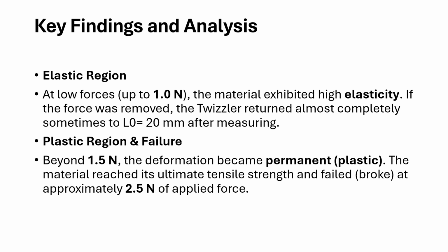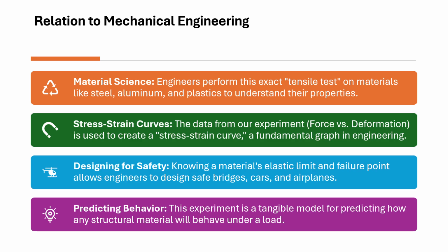So for the plastic region and failure of the Twizzler, it was beyond 1.5 newtons, where the deformation became permanent or plastic, and the material reached its ultimate tensile strength and failed at approximately 2.5 newtons of applied weight or force.